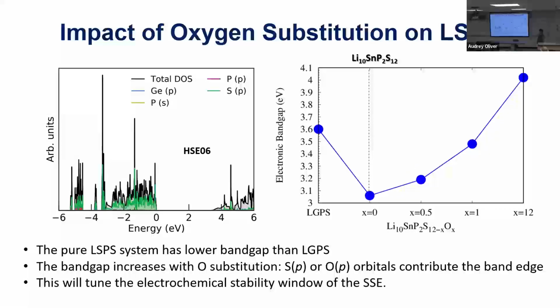Okay, so we calculate the band structure. If you use standard DFT, it underestimates the band gap. That's why we use a hybrid functional. And we have this gap, it's an insulator. Once you replace germanium with tin, the band gap decreases. This electrolyte should be an insulator, so its band gap should be large. So it's not good, and that will also restrict how thick you can use. But if you replace sulfur with oxygen, you can recover. Actually, you can increase the band gap. But what about conductivity? We can find out how to optimize electronic properties and ionic conductivity somewhere here.